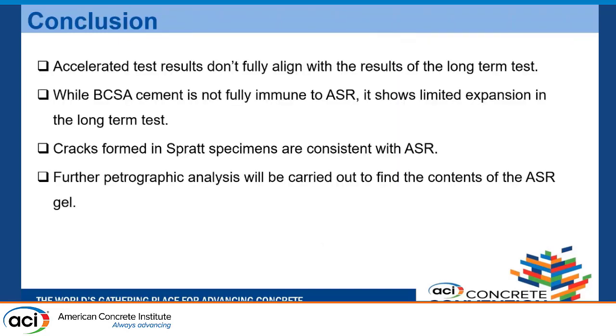Based on these results, I can conclude that the accelerated test results don't fully align with the results of the long-term test. So if a concrete mix is judged just on the results of the accelerated test, that may not be an ideal representation of how the concrete will perform at site. We need further results to validate the results of the accelerated test and even do further analysis. Also, BCSA is not fully immune to ASR, but it does show limited expansion in the long-term test, which is a good sign.